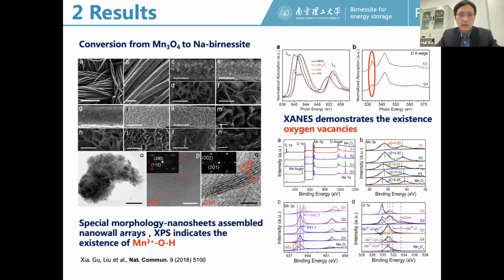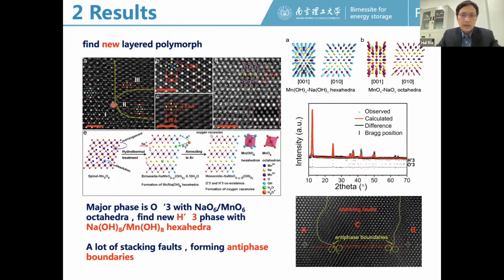After that, we look at the atomic structure. And when we look at the atomic structure, it is very interesting that we can find two types of atomic arrangements. So first we look from this 001 direction, and we can find two types of atomic arrangements. For figure C, this is the atomic arrangement according to the normal O3 layered structure. However, for this figure B, this atomic arrangement has never been reported in previous work. And from this 010 direction, they all look the same.